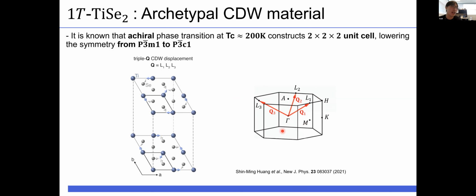As you can see, Q points have an L component. This is the reason why the displacements in the upper layer and lower layer have opposite directions. This displacement lowers the symmetry from P-3m1 to P-3c1. The bar in the name of the space group means the existence of inversion symmetry. So this material has been regarded as achiral for a decade.